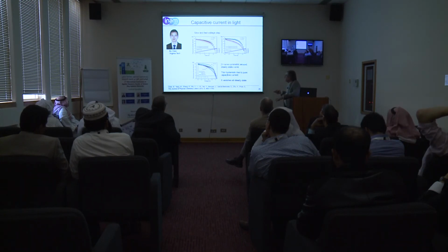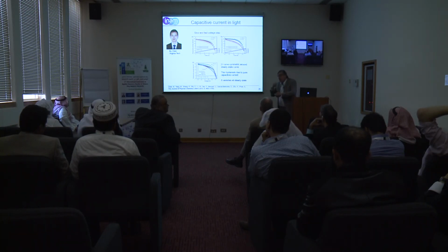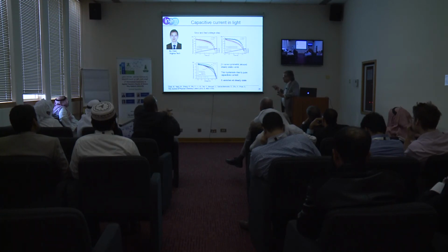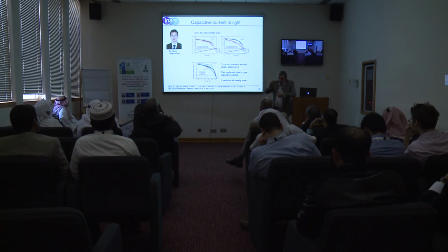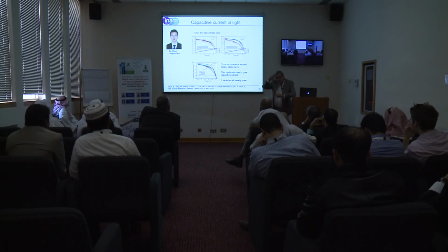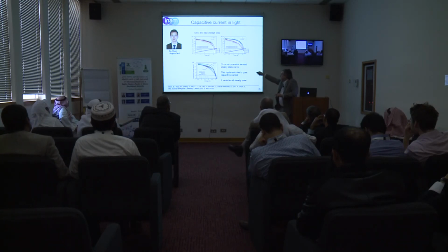So now this work was done by Bo Chen and also Kai Su, and they contacted us for interpretation. So it's a very nice work because we know the capacitive current, but the perovskite has another current that is not capacitive. But they succeeded to make cells that are very, very capacitive. So the hysteresis is totally capacitive. And this is very beautiful because a capacitor has a transient decay, so the hysteresis here is very easy to understand. You have a decay, so if your voltage step is done very slowly, in each case the decay goes to the JV curve. And it doesn't care if you go forward or backward, you do the same.